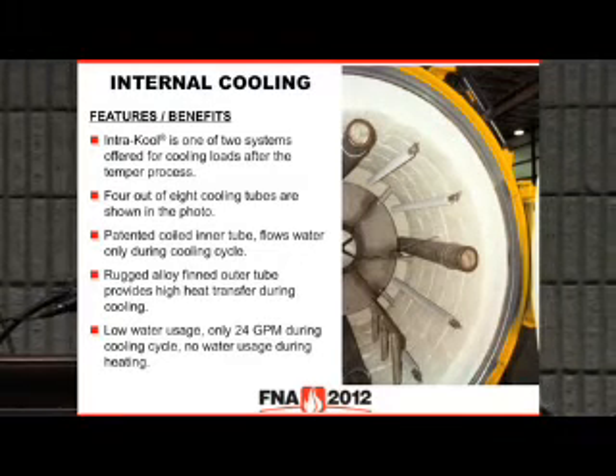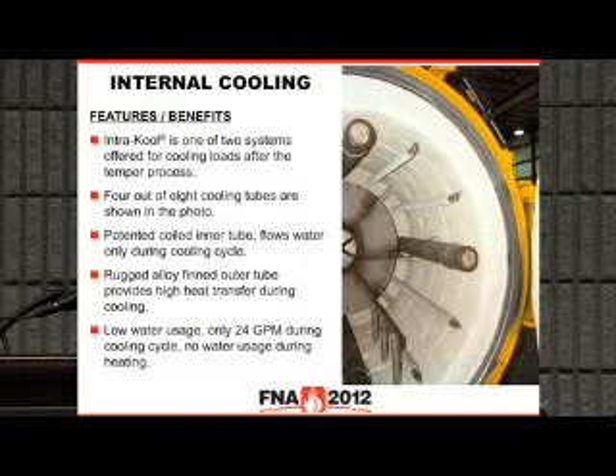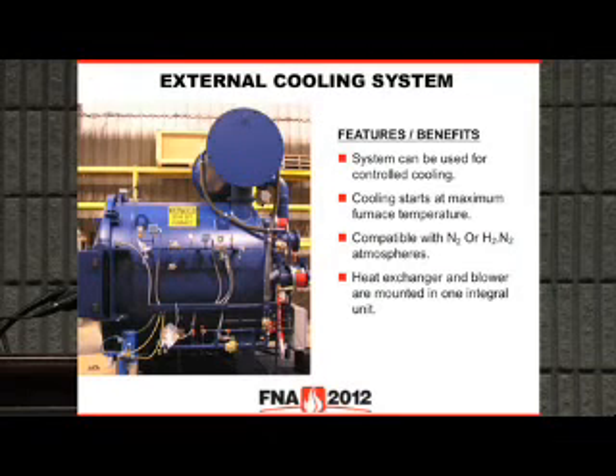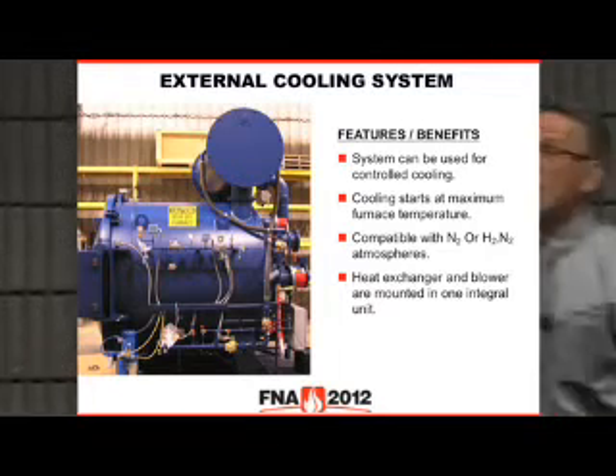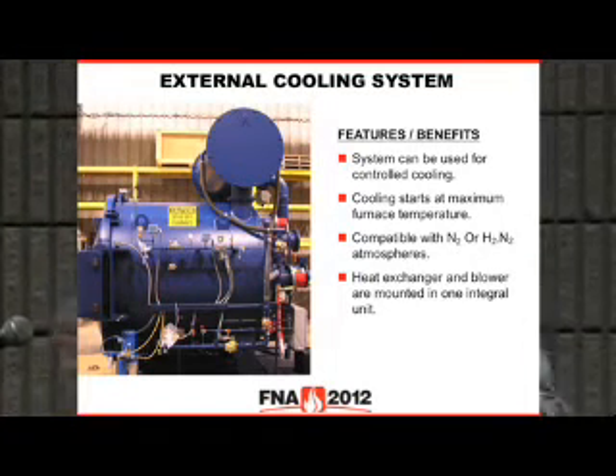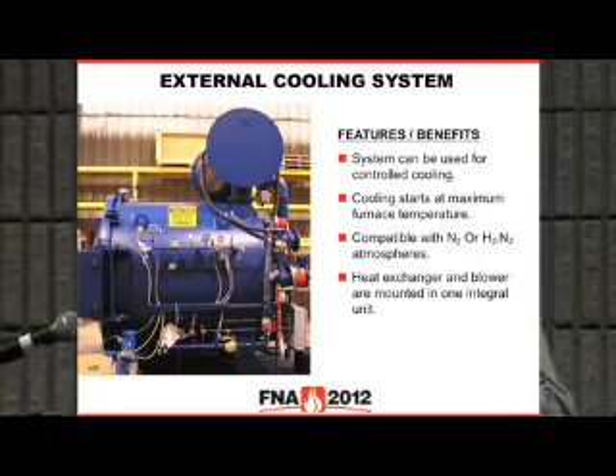Water usage is low. This design runs about 3 GPM per tube, and it's a very simple system. What temperature is that water? Room temperature. Yeah. So there's some steaming that happens as the water first turns on, and so the tube basically has no water in it from the last cycle, and then during the cooling stage, which could be at 1,000 degrees or 1,200, we then open a solenoid valve and the water starts to flow through this helix. This is all within the cooling tube itself, and then at the end it returns back and floods the helix and floods the ID of that cooling tube.